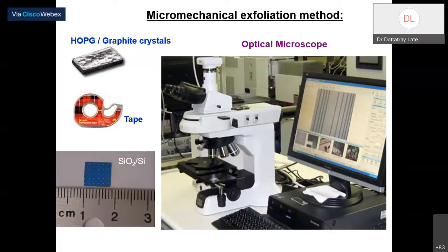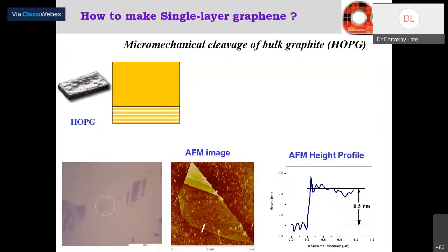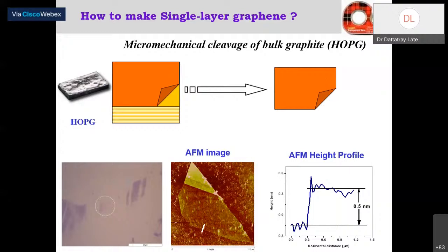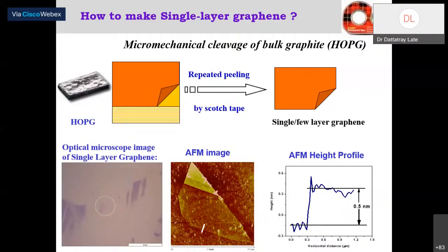So I can easily identify under an optical microscope the thickness of one layer, two layer, or multi-layer graphene. Okay, so what will we do? I will take this HOPG crystal or graphite crystal, whatever is available, and put the scotch tape or any type of transparent tape on this graphite crystal. I will put this tape and take it out. I will fold that tape repeatedly a few times, maybe 5-10 times.